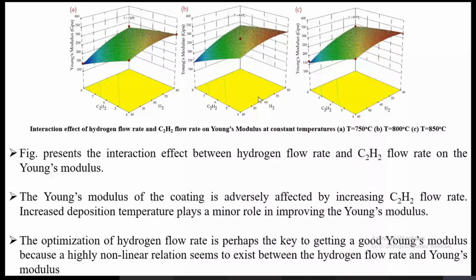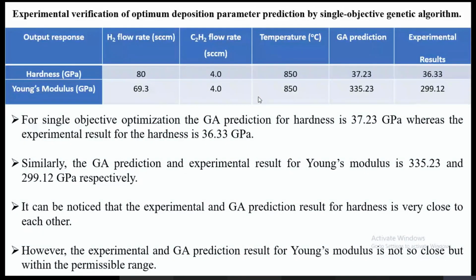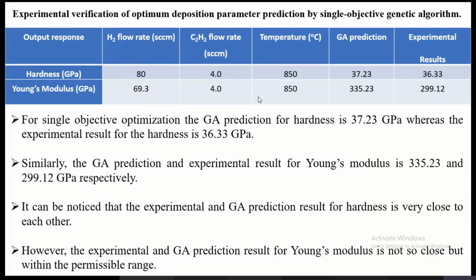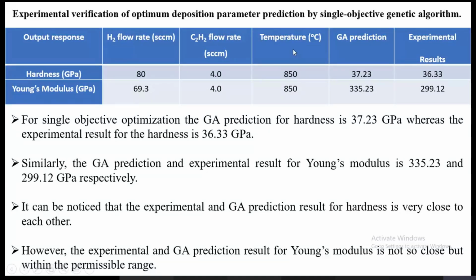We also observed that in this interaction plot. Now, in this case, we used the technique of genetic algorithm, but a lot of techniques are there. Anyone can use any kind of technique by considering a particular data set, and you can use other techniques to predict the result. Here we used two different methods: one is the single objective genetic algorithm, and we also used the multi-objective genetic algorithm. With the single objective genetic algorithm, we considered three input parameters: the hydrogen flow rate, the C2H2 flow rate, and the temperature. For these parameters, we predicted a value using the genetic algorithm.